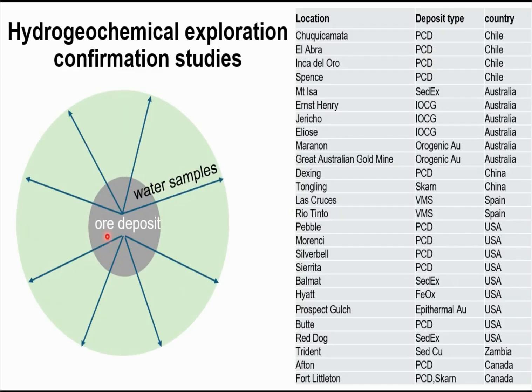So the wheel on the left is an indication of if there's a subsurface ore deposit and we collect water samples above it and then radially out, we can use the metal isotopic composition of the water within about 1.5 to 2 kilometers of the deposit to identify copper iron sulfide and copper sulfide mineralization. And then we went around the world and we sampled waters from every single one of these deposits, which include all of the other types of copper deposits that we currently mine copper from.